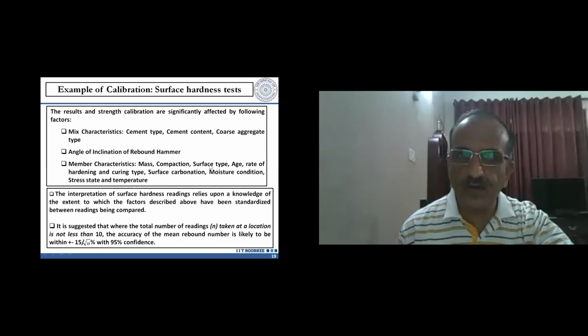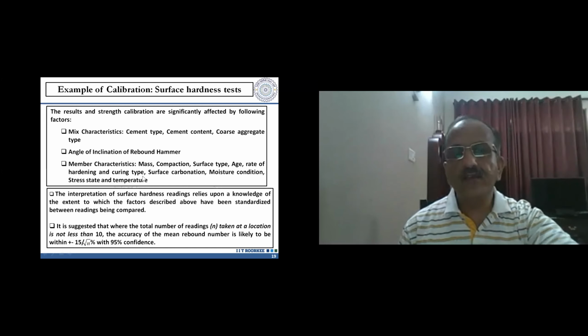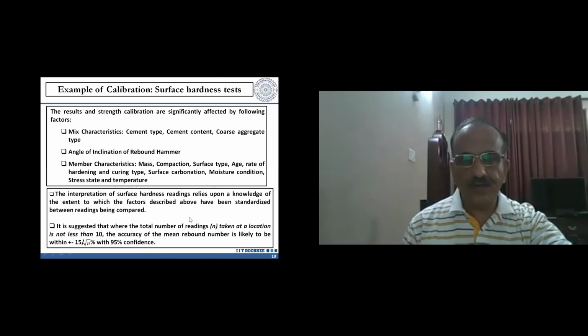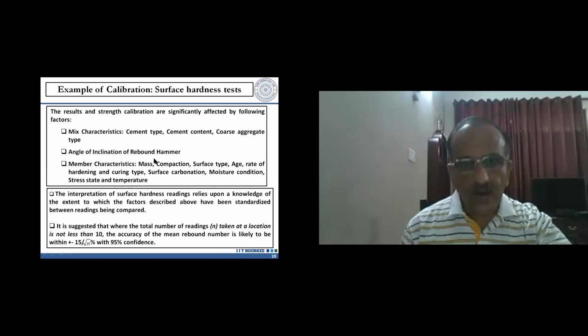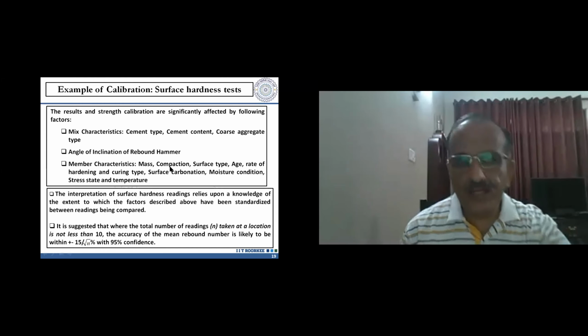If you are using cardboard shuttering, then what will happen is that field rebound numbers will be more, because cardboard shuttering, plywood shuttering will lead to water absorption and it will make the surface hard. You will get higher rebound numbers, which are misleading. So you have to apply a correction. That is one example. Similarly, all these factors will influence the rebound number. So all those are to be taken into account, and only then can you develop a proper calibration chart.